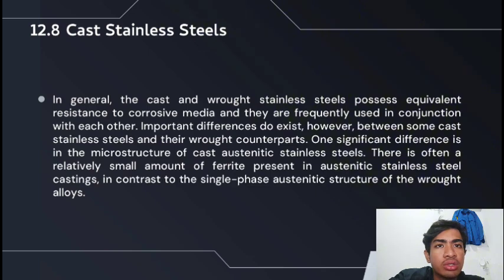In contrast to the single-phase austenitic structure of the wrought alloys, the presence of ferrite in the casting is desirable for facilitating weld repair, and the presence of the ferrite also increases resistance to SCC. There have been fewer failures with cast stainless steel in comparison to approximately equivalent wrought compositions.